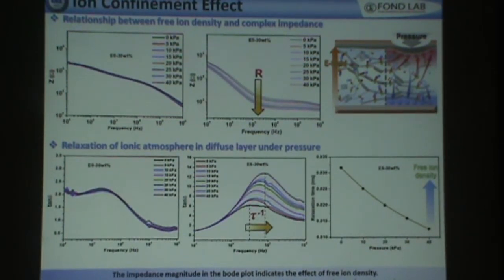So you can see from the relaxation time graph that as pressure increases, we have a high free ion density, due to the fact that the relaxation time also decreases. This is due to the fact that the ions that were initially trapped are being released as the pressure increases.